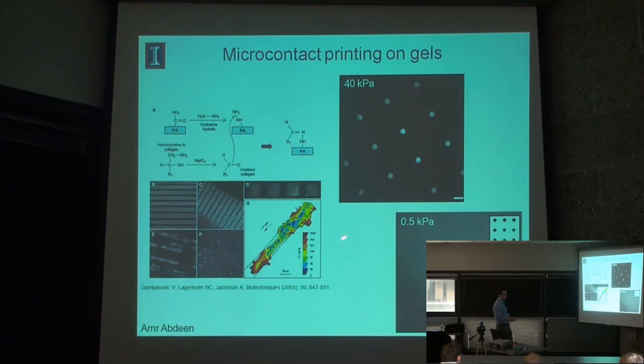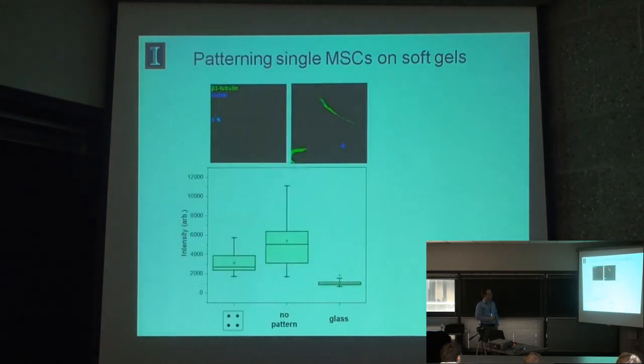And it was really tough to get it on the soft materials, but we are able to pattern cells. These are single mesenchymal stem cells, patterned on gels with half a kilopascal of stiffness. So we decided to see what patterning would do. Here's an example of an interesting early development that we're currently investigating, where we found that in patterned culture, we see very different mixtures of these lineages.